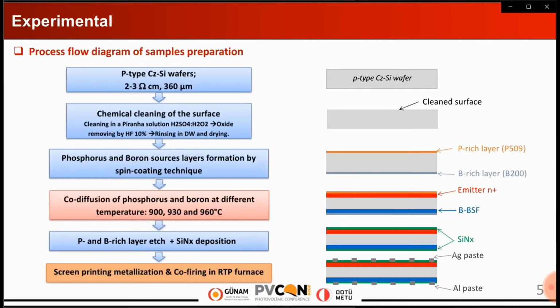After the diffusion of phosphorus and boron from the spin-coating deposited source layers, the wafers were immersed in a bath containing a concentrated HF acid solution to remove phosphosilicate glass and borosilicate glass. After this, the wafers were rinsed with deionized water and dried. The deposition of silicon nitride anti-reflection layer on both sides of the structures is followed by the formation of electrical contacts on both sides through the co-firing of screen-printed metallic pastes.